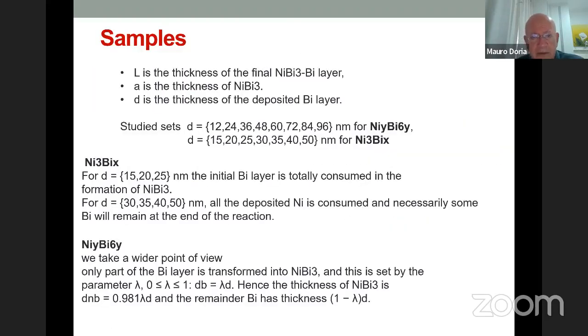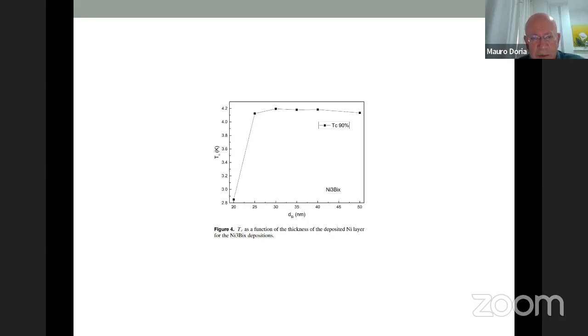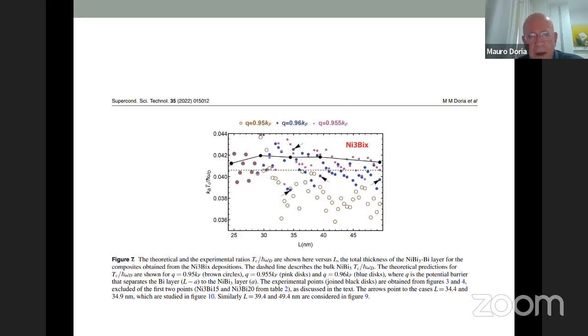So then we look at these two systems with their particular thickness and so forth. We want to describe these TC oscillations. This is what we found in this system with nickel 3 bismuth. This is the critical temperature times the total thickness of the system. We find that it's very sensitive to the height of this barrier, which is a barrier approaching the Fermi surface. And as we vary the thickness, we see that we have many possibilities of critical temperature in this range, not a very large range, but some range.